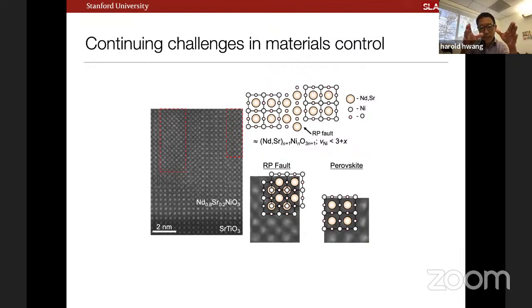And the issue is that we're growing this perovskite phase in fairly extreme tensile strain. And so the system is trying to address this strain by inserting these intergrowths. And these are basically frozen in from the perovskite compound going into the infinite layer structure. And so in summary, what we find is a lot of, let's say, bulk volume measurements are quite robust in the presence of these defects. Certainly for things like transport, this is the likely origin of the scatter that I just mentioned to you, or one of the important contributors.